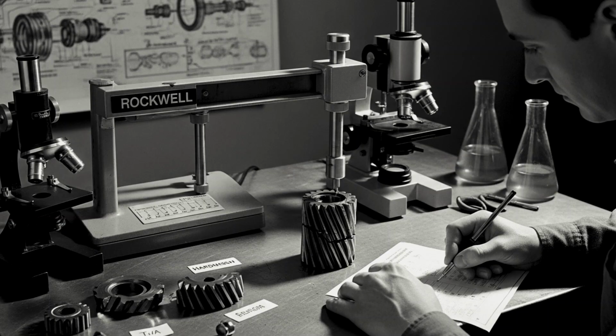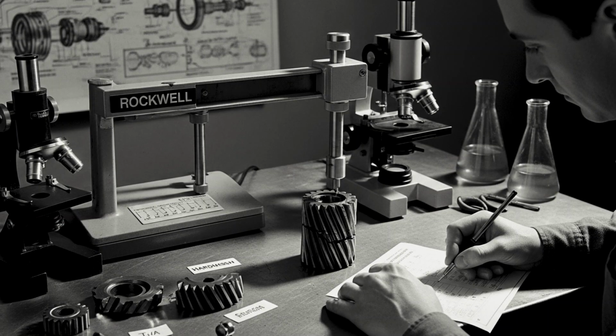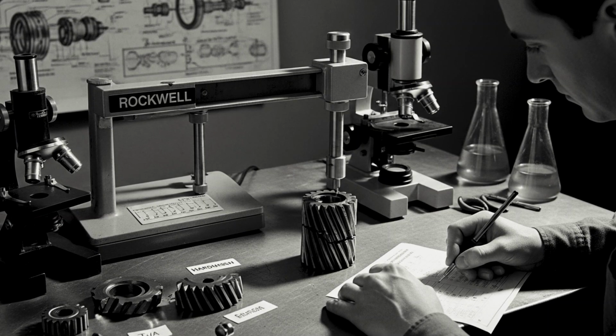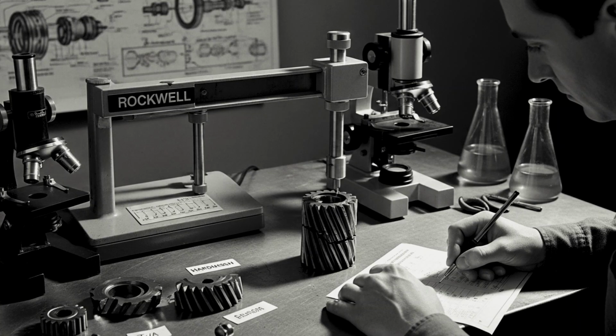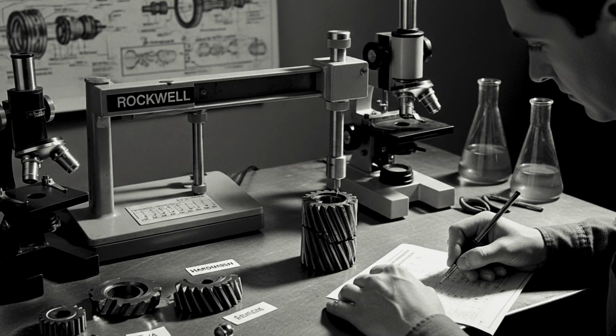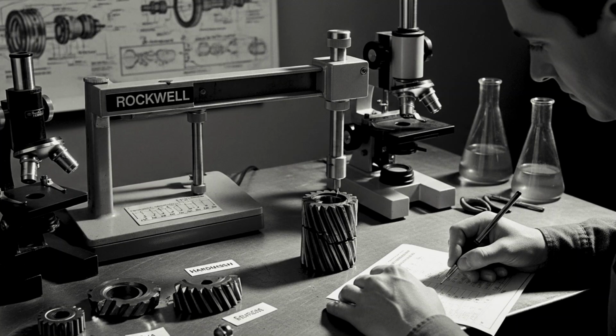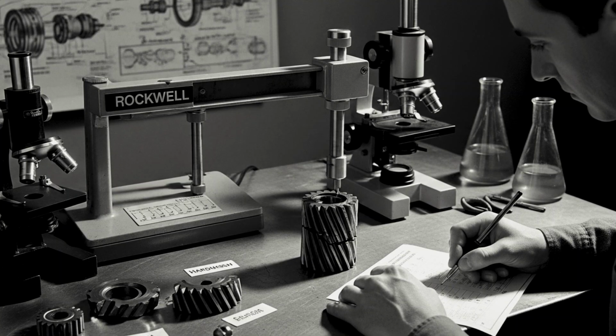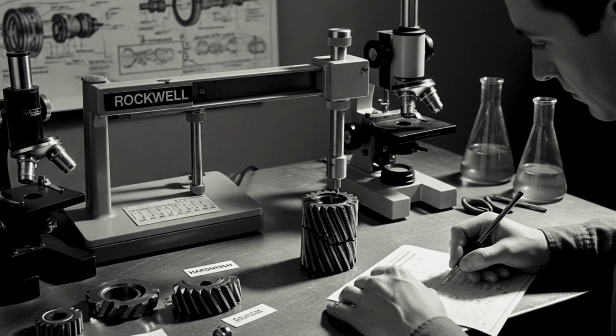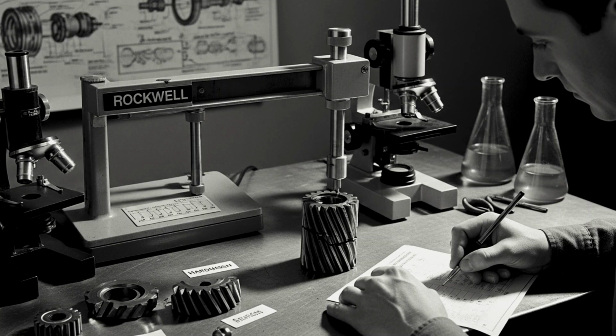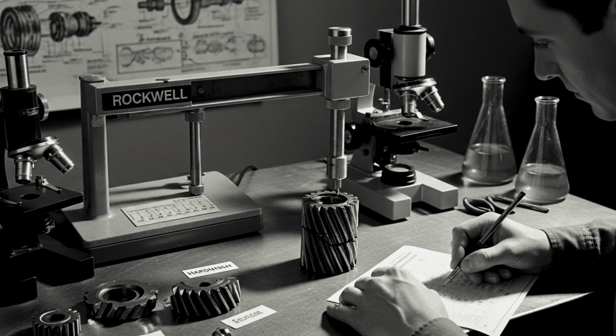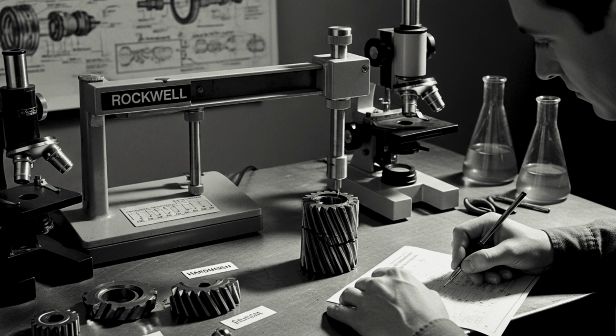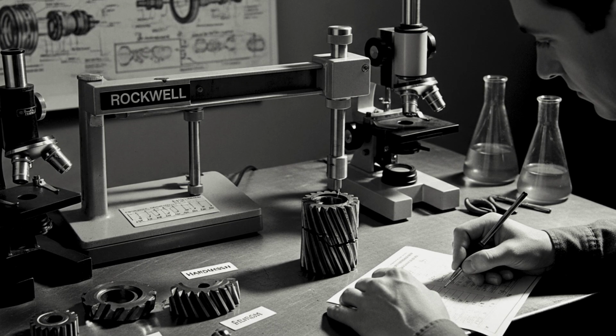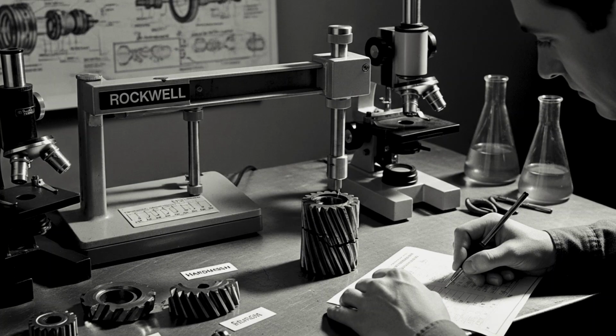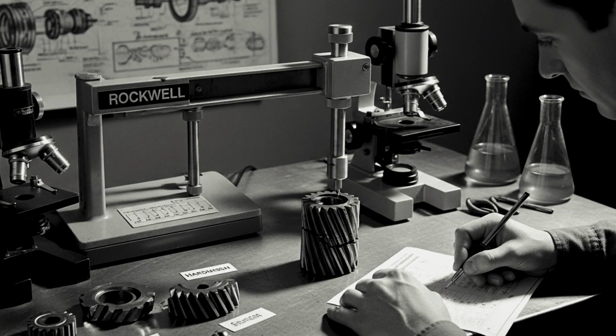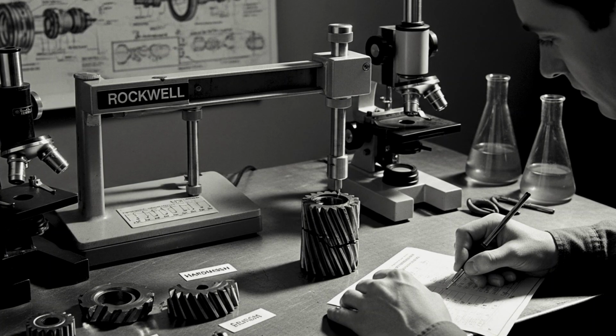He tested several spots on the gear. Each time the surface measured between 62 and 64 HRC. Then he cut the gear in half and tested the inside. The middle part measured 52 HRC, which was much softer. This difference showed that the gear had been case-hardened. That means the outer layer was made very hard through heat treatment, while the core stayed softer and tougher. That process was normal for gears. It gave them a hard surface to resist wear and a softer inside to absorb shocks.